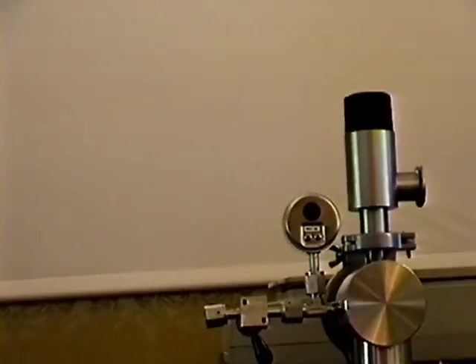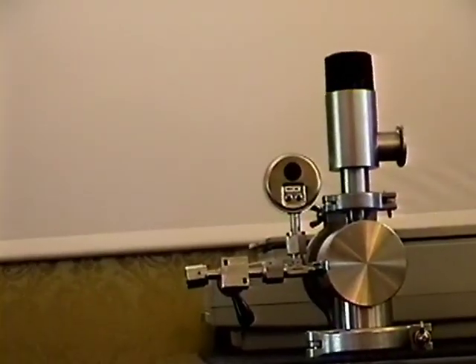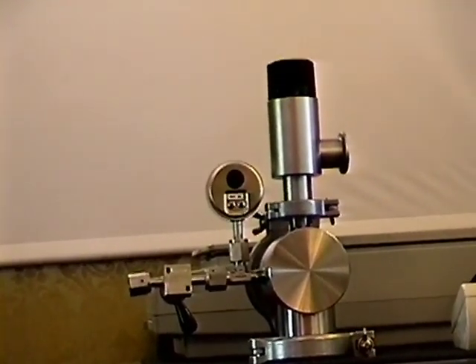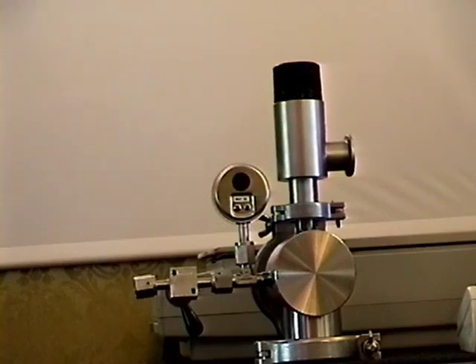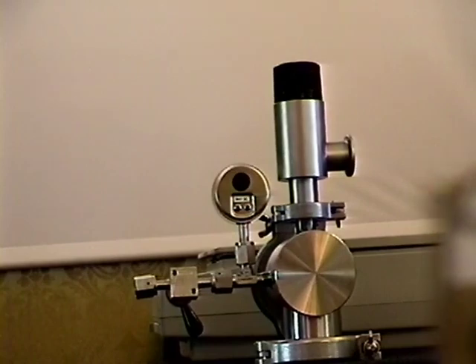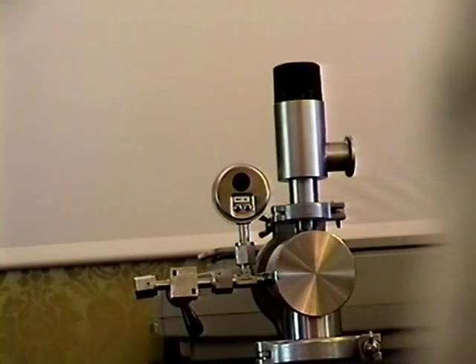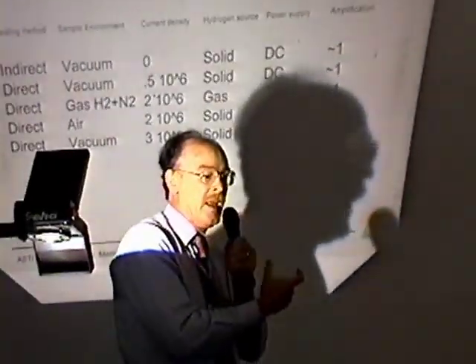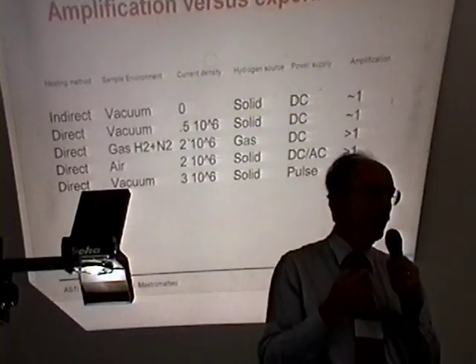Okay. You use a current density extremely large, so that this regime of pinching effect, maybe you overcome the pinching region. Do you think about this aspect about neutron emission? Because you want clean energy, not neutron. Yes, you are right. With the new samples that I can show you immediately, I probably, in the formula, you can see that there is another important parameter, the volume of the sample. If you would like to generate energy, you need a volume of the sample. And using low current densities, you can have quite a big amount of energy using a quite big volume of the sample.